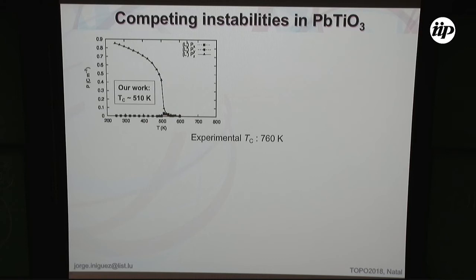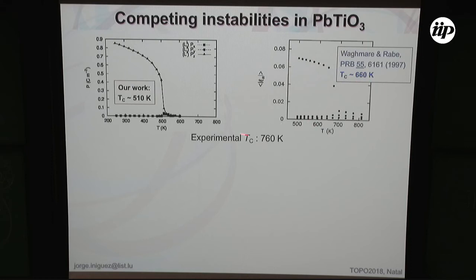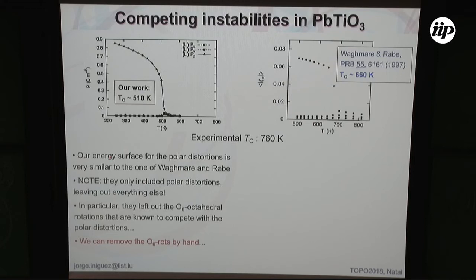Comparing the phase transition of lead titanate as calculated by our model with experiment as a function of temperature, the profile compares very well — but there is one problem: the transition temperature is 510 kelvin in our model, while experimentally it is much higher. This was very frustrating because lead titanate had already been studied with the simpler approach introduced earlier by Rabe and Joannopoulos, and they got a phase transition much closer to experiment — which was definitely not what we were expecting.